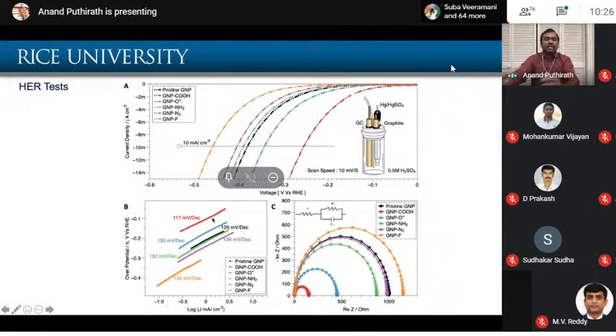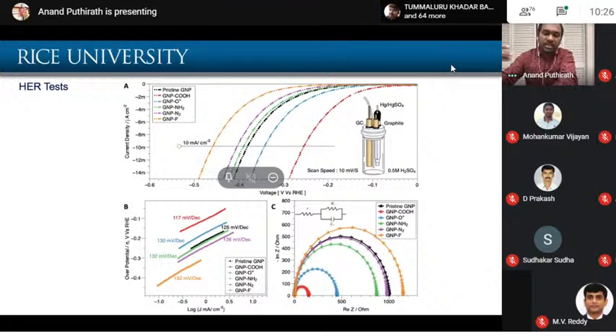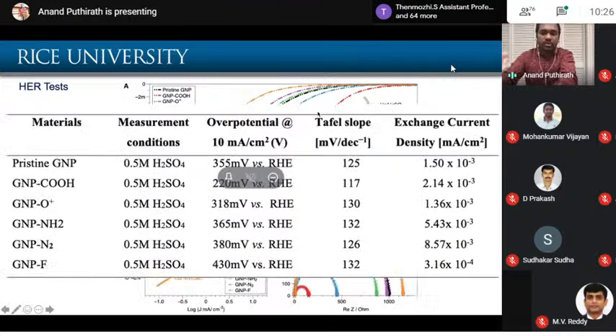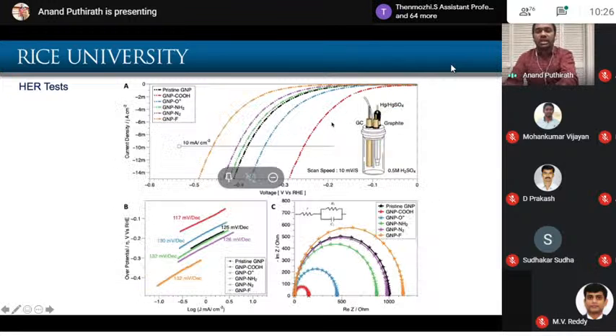And when we do the HER test, basically hydrogen will turn into a radical form and be adsorbed on the surface, and then another hydrogen, through charge transfer, will form H2, which will basically evolve from the system. And you can basically characterize this. People who work on the system know how to do this, but you want to split the water. Usually you want to apply 1.2 volts across the system so that oxygen and hydrogen separate and they evolve. But if you have a catalyst, you can reduce this voltage window to lower values.